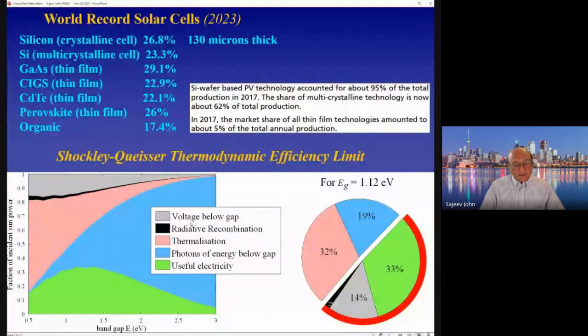Laboratory cells, on the other hand, have reached a much higher efficiency, and I just list some of the different efficiency records that have been set in laboratories. For crystalline silicon, it's now at 26.8%. That has only increased by about 1.8% over the past 25 or so years. For multicrystalline silicon, which is less expensive, the record efficiency is 23.3.